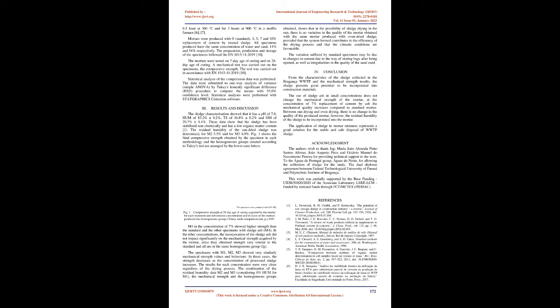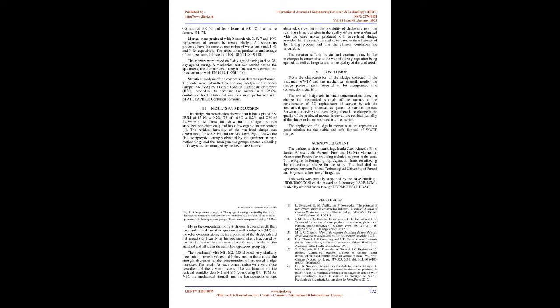Method 2 and 3: a sludge sample was left in the sun to dry naturally, as in Costa's 2011 work, for a period of 7 and 15 days (M2 and M3 respectively). In this case, the residual humidity was determined after the drying period in the sun.